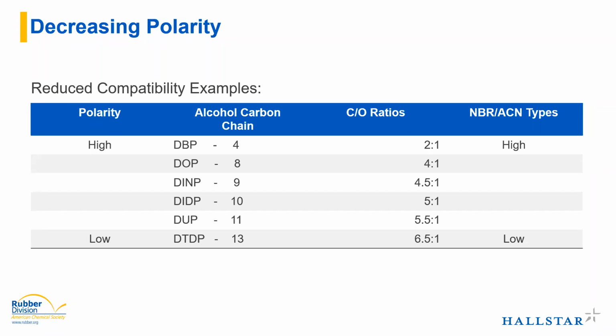This takes a chunk out of that polarity chart that we showed before by putting these plasticizers in order of high to low polarity and showing that they would be compatible with a high polarity, high ACN content NBR versus the low ACN NBR or low polarity NBR.